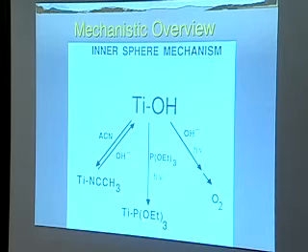And then finally, obviously, in the absence of those materials, hydroxide could bind, and you would go to oxygen. We obviously know that when you electrolyze hydroxide, it does generate oxygen, so that path is correct. I will tell you that if you add a few millimolar of this phosphite into your solution, it is dead. You oxidize nothing at that point, and you can't just wash your electrode off with a little bit of water and restore it. The only way to get your nice single crystal TiO2 back as a photoelectrode is to polish it down. So that is binding, just like I said.